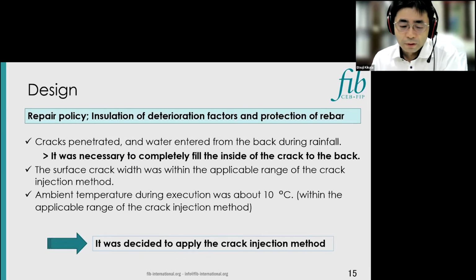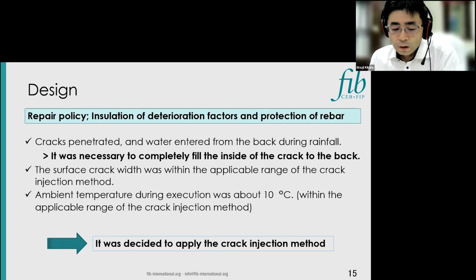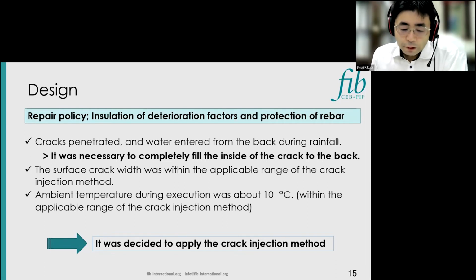About design of intervention method. The repair policy was set to suppressing the invasion of deterioration factors and protecting reinforcing bars. There were also repair methods other than crack injection that were suitable for these repair policies. However, since the target crack was penetrating and water entered from the backside, it was necessary to completely fill not only the crack surface, but also the inside of the crack all the way to the backside. Therefore, the crack injection method was the most suitable.